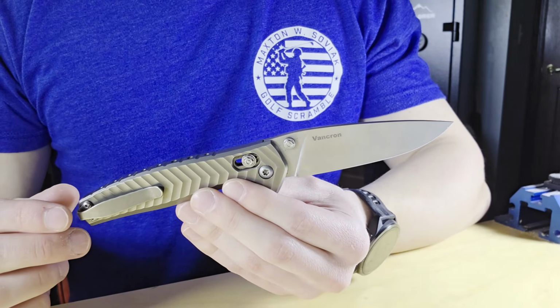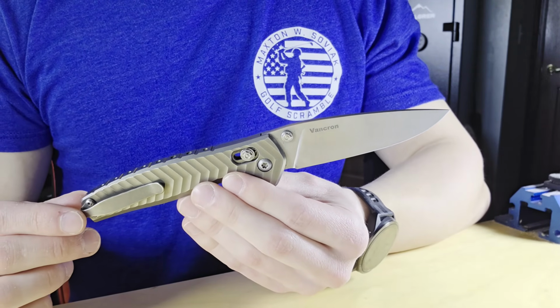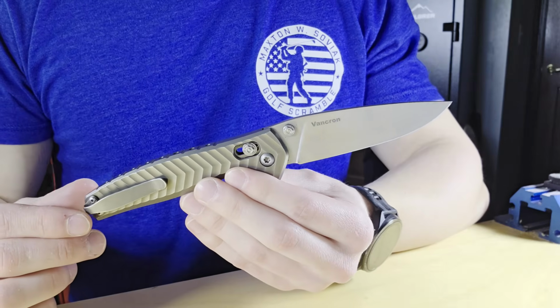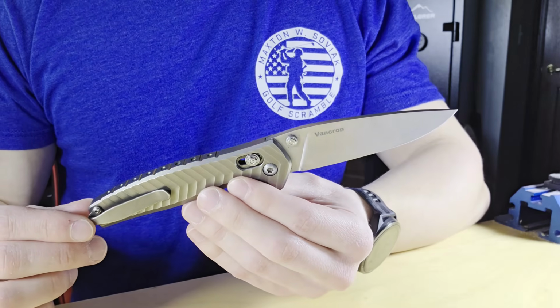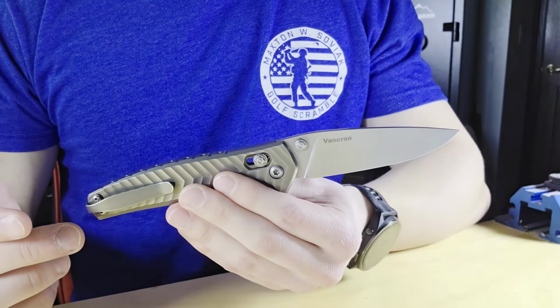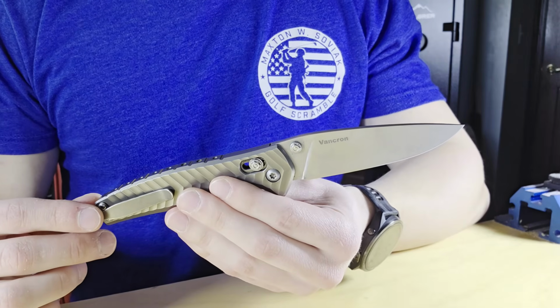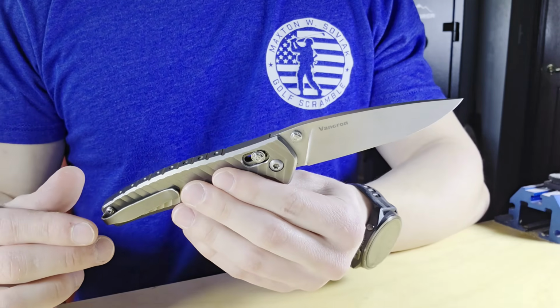It sharpened very much like MagnaCut, 4V, and Crucible Wear, that class of steels, which is impressive considering the carbide volume and the hardness of this blade. And all of that's more than likely due to the low retained austenite from Roman's custom heat treatment.